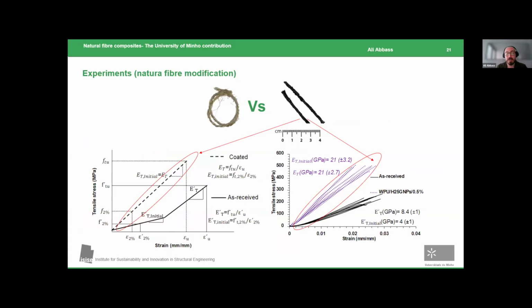Moving to the most mechanically important part of the entire modification, which is the stiffness. As you can see here, we solved the issue of non-unified stiffness throughout the tensile loading. So this solution can now be used in a reproducible design. You would have a unified stiffness throughout the strain, throughout the tensile load, with a representative value. Wherever you take it, the phase of the tensile behavior of the yarn is going to be identical. This is very important for the designers.